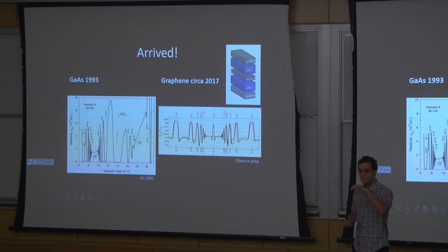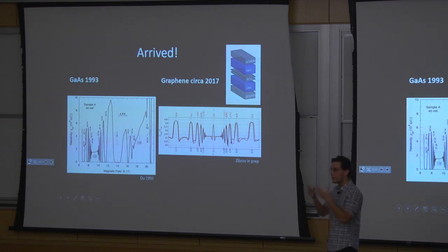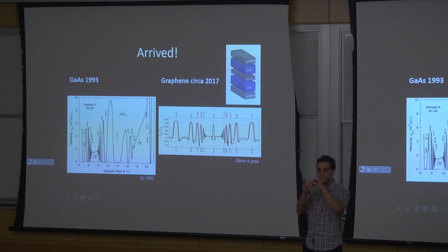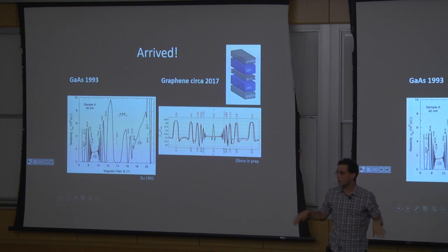It turns out that different facets, little grains of metal, have slightly different work functions. So if you're evaporating some metal, these different work functions on the different facets look, from the point of view of the graphene, like a slightly different potential here and a different potential there, and so on. And that was the main source of disorder in our sample.